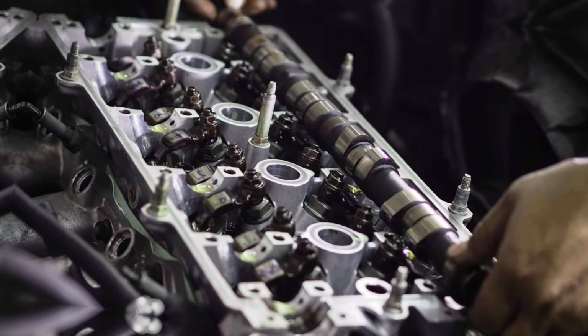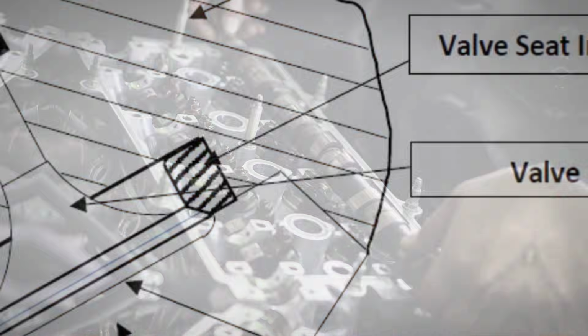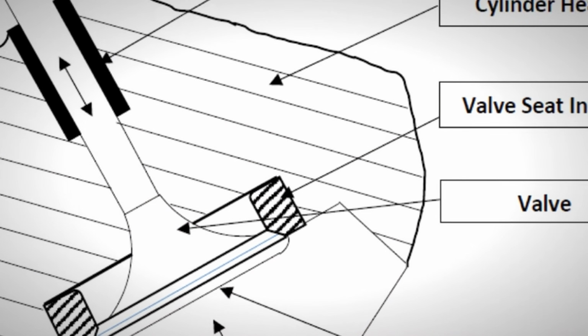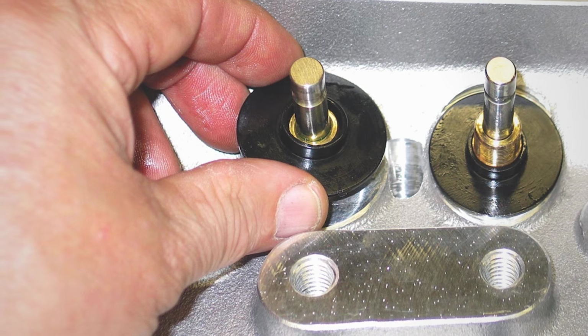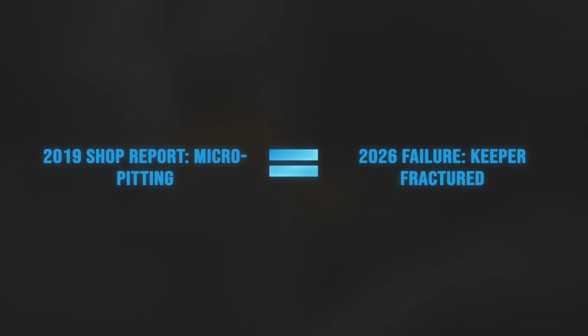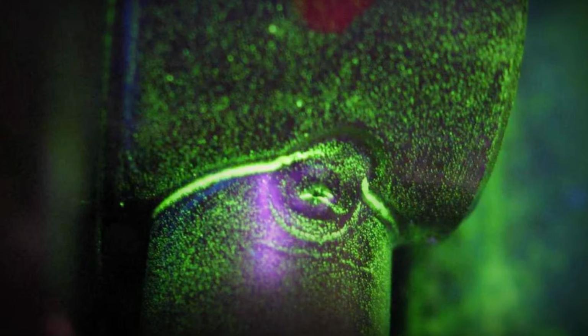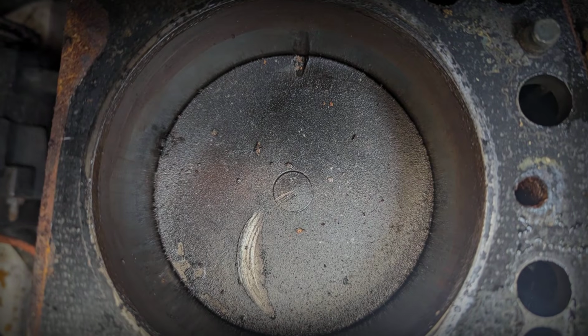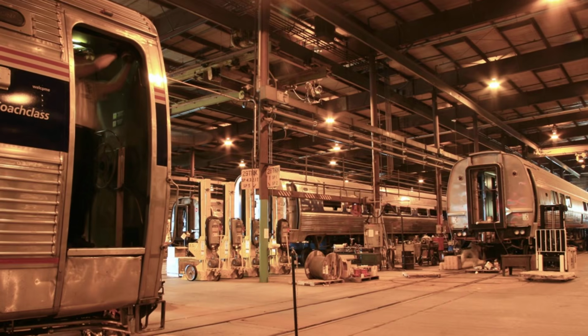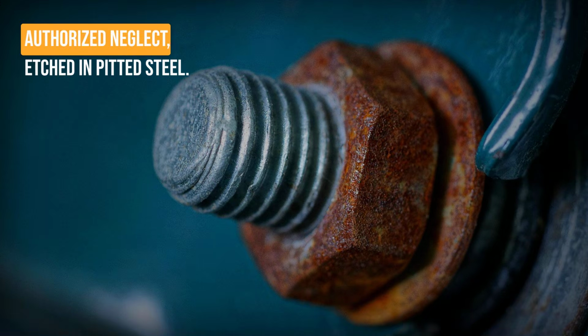Over tens of thousands of cycles, the reduced contact area concentrates stress at the corroded interface. Fatigue cracks propagate along the keeper shoulder. The final fracture occurs well below the nominal tensile yield limit. The result is a textbook case of corrosion-assisted cracking. The evidence is not theoretical. It is a shop inspection report, a metallograph, and a signature of deferral. The failure is not random. It is authorized neglect, written in pitted steel.